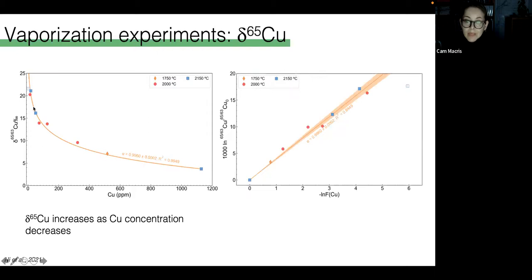In this plot on the right, I've plotted the same data as the plot on the left, but the axes are now different. So here I'm plotting it as the natural log of the isotope ratio, the 65-63 copper ratio in the experimental residue over the copper isotope ratio in the starting material. And then the x-axis is the negative natural log of the fraction of copper remaining. And here we get a very strong linear relationship defined by all of the experimental data. But why would we do this?